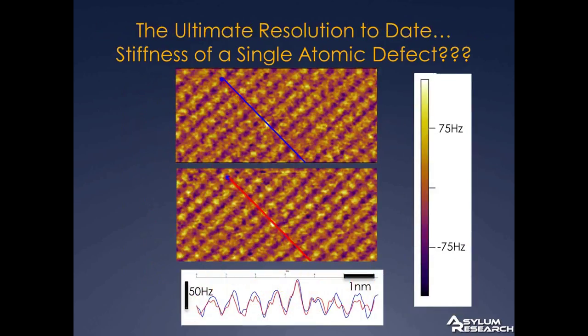Taking that same data set, I just made a couple of sections through it and plotted those here. The top is in blue, the bottom is in red, and I overlaid those two on top of each other. The vertical scale here is 50 hertz, and the lateral scale is 1 nanometer per bump, more or less. What we see here is a significant change in both the images, and again, these images are 5 or 10 apart. There's a significant increase in the stiffness over that little hole in the sample.